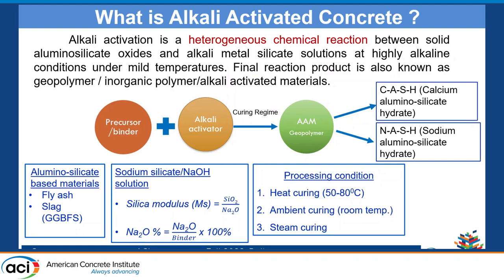The alkali activator has two solution parameters. The first is silica modulus (Ms), which is the mass ratio between silicon dioxide and sodium oxide contained in the solution — this gives an idea of the silicate concentration. The second parameter is sodium oxide content, expressed as a percentage of the binder, which gives an idea of the sodium hydroxide concentration of the activator.